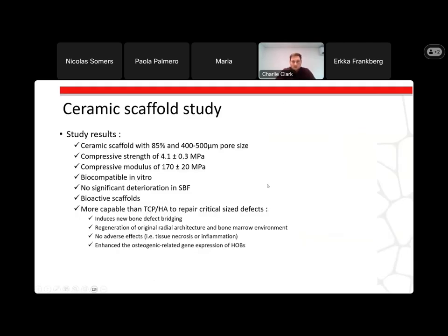To take away from the study results, they were able to make a ceramic scaffold with 85% porosity and 400 to 500 micron pore size, very similar to bone structure. Good compressive strength and modulus. It was biocompatible in vitro. There was no significant deterioration in simulated body fluid. The scaffolds themselves are bioactive, and it was proven to be more capable than TCP and HAP to repair the critical size defects.